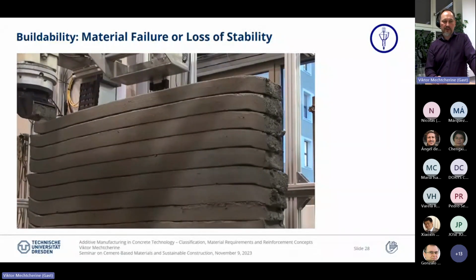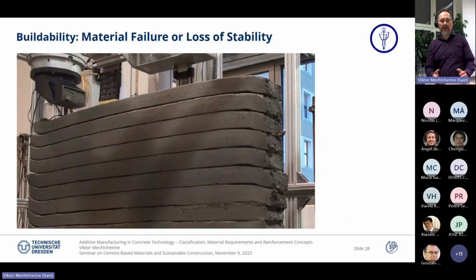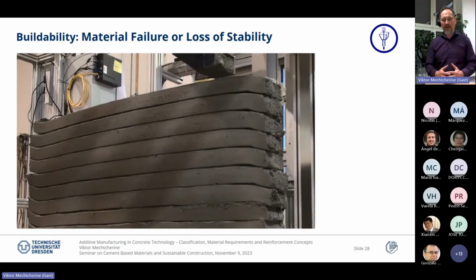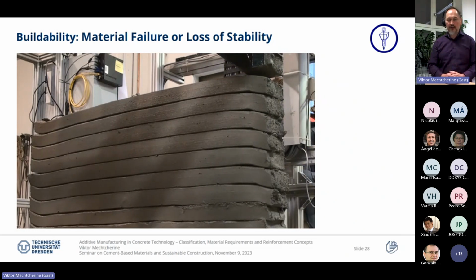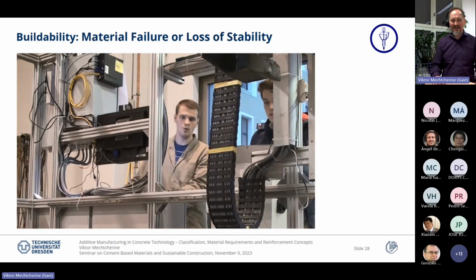And buildability, I just repeat myself, is a capacity of the material to carry the load of the upper layers coming when we are in progress. And this is what we do in the lab. Actually, we wait till this all fails, and you see a little bit surprised expression on the face of my colleague. Well, he shouldn't be surprised because we actually printed on purpose as long until we reach this ultimate state, the failure, and then we can, from this measurement, actually test if our prediction of buildability is valid or not. So we need also this kind of experiments where we have kind of failure.